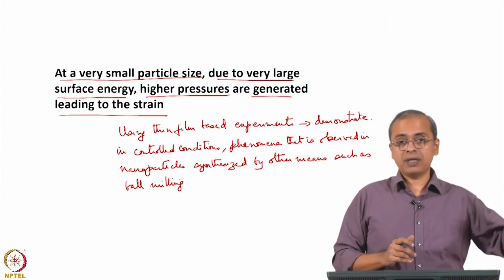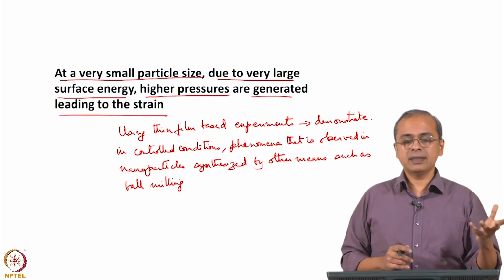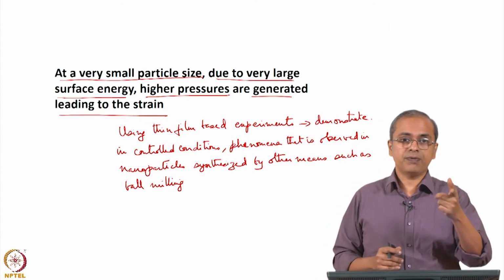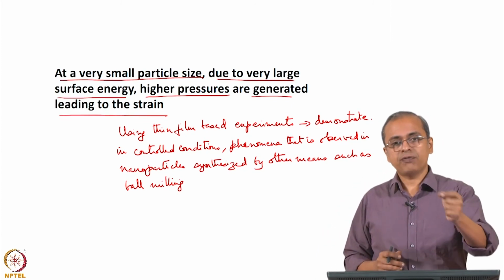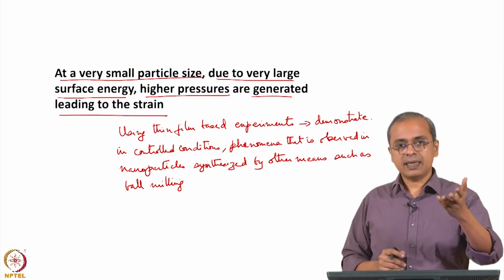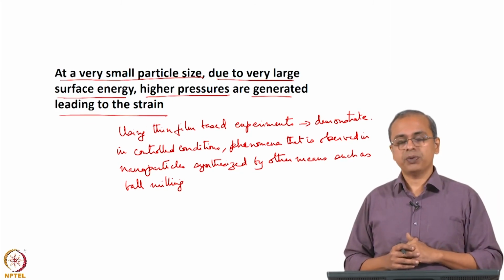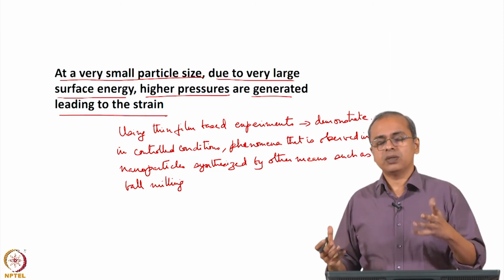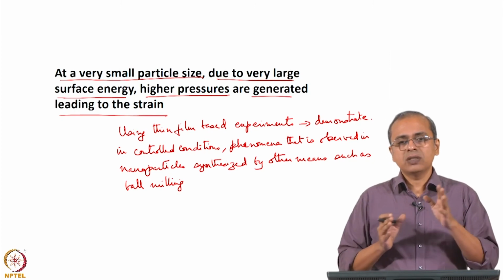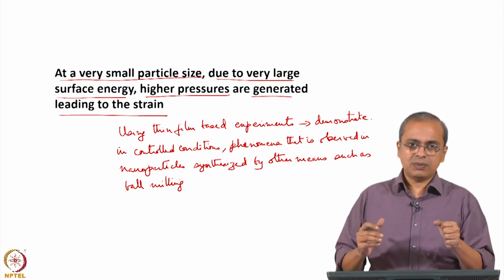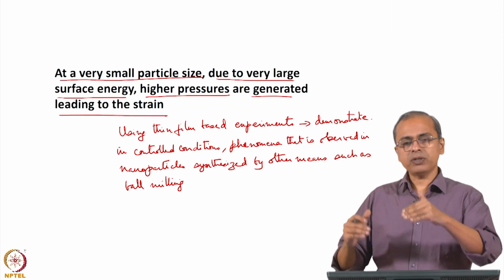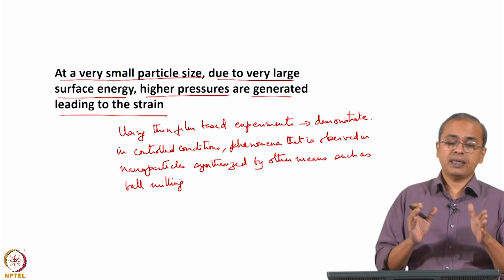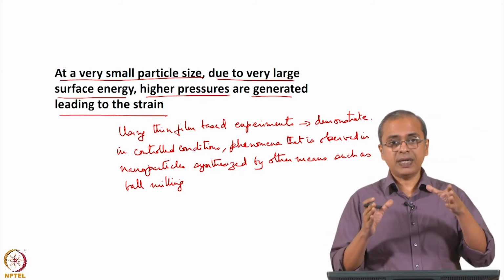Ball milling gives a different kind of conditions to the particles, they are being hammered, they are broken down, but it could maybe introduce impurities. You are already talking of a nanoscaled material, in that even if you have a few atoms of impurities, that is a significant percentage of impurities, and you may have variation in sizes, you may not have enough control to say that you got only this particular size. So, you have those peculiarities associated with it. The thin film, on the other hand, you can measure the thickness of the thin film. Usually thin films are made under high vacuum conditions and very clean conditions.